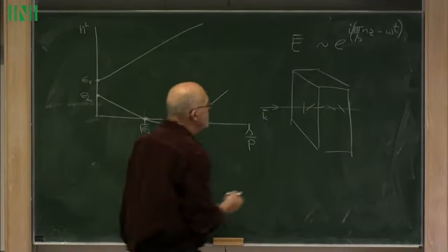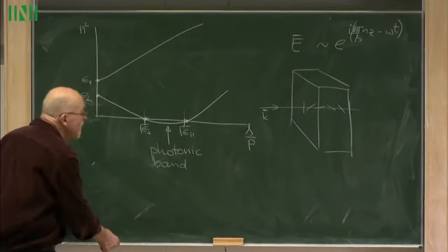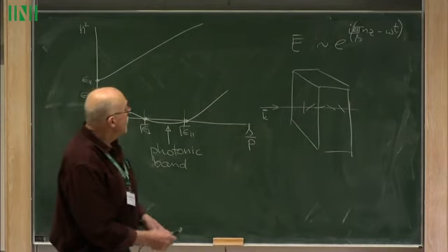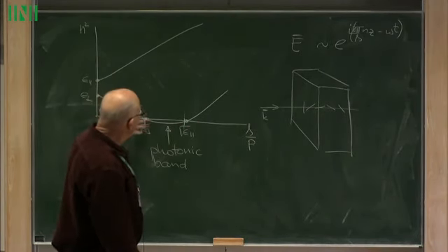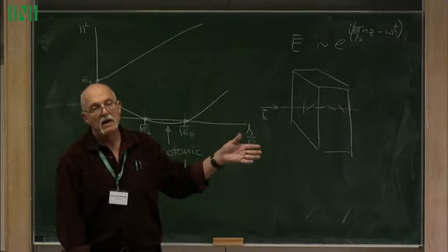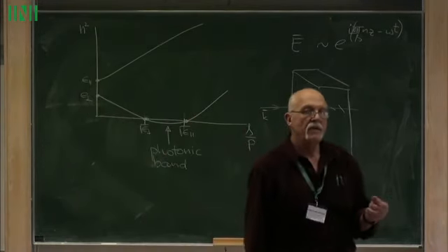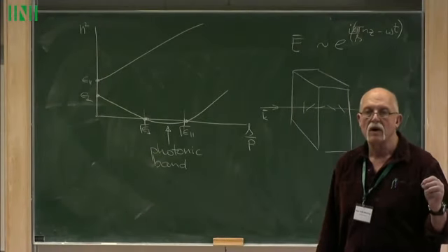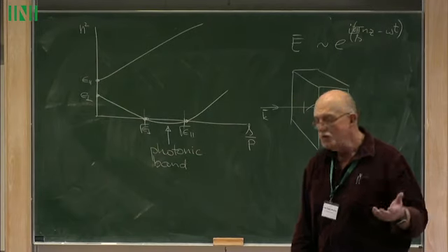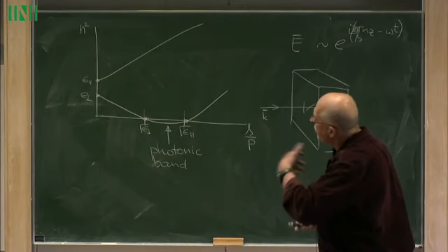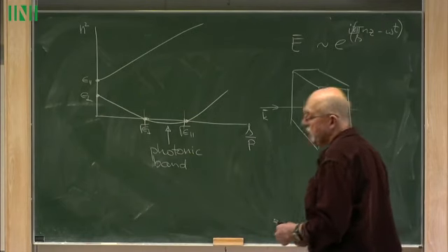Off-axis solutions are just not tractable, unfortunately. So we find this really fascinating thing that we have this photonic band gap, which is simply produced by the periodicity of the crystal. And it has nothing to do with the chirality of the molecules per se, other than that the periodic structure is produced by the chirality.